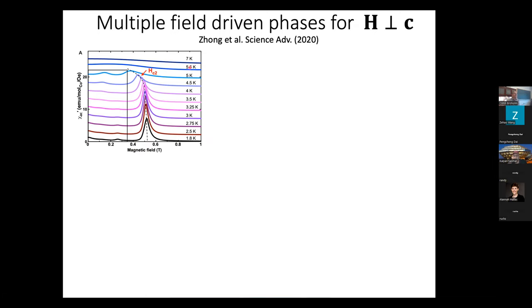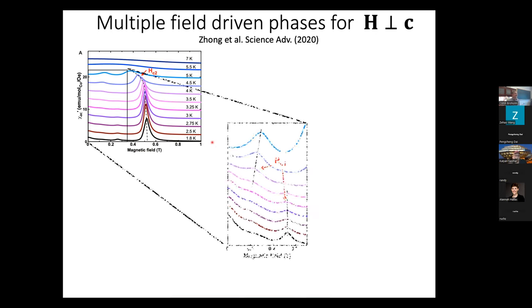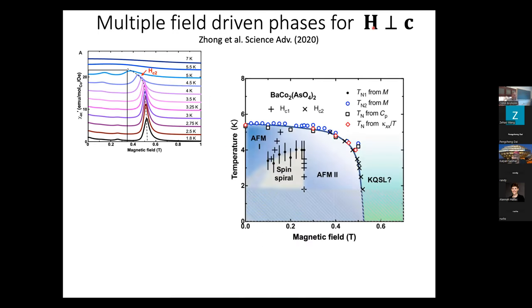And then as you heat up, get up to around 5 or 6 Kelvin, then you leave the ordered state entirely. If you look a little bit more in detail, then you find additional features in the AC susceptibility at much lower fields, indicating additional field-driven phase transitions. Now, all of these measurements are done with the field in the basal plane, perpendicular to C, and that is really where you get the strongest field response. When you apply the field along the C axis, if the sample doesn't fall off because that's the hard axis, then in many cases you'll be dominated by the impacts of a small deviation from being completely perpendicular to the plane. So the small in-plane component is difficult to avoid, in fact, because it's so anisotropic. Just a couple of degrees will cause you to be impacted by this in-plane component. So we're going to mostly look at the properties of the material with the field in the plane.